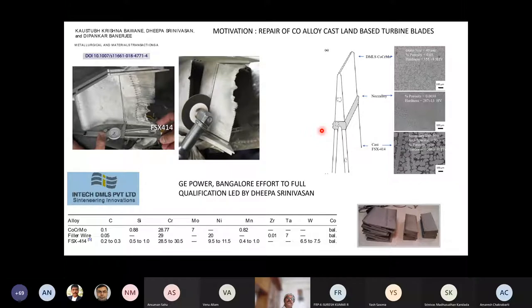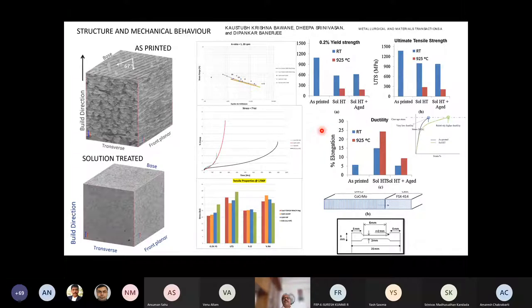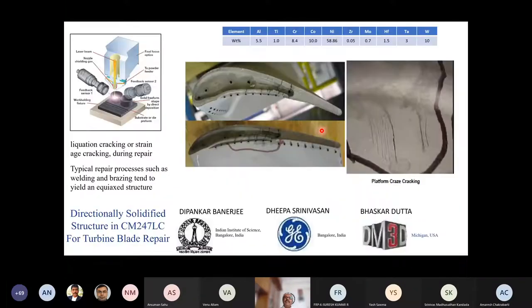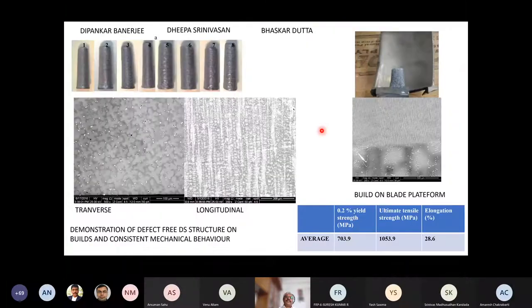So this was done for the repair of turbine blades, and this work was also done in collaboration with Intech DMLS. That's Professor Banerjee's work. I was not a part of it, but I just wanted to show it. So these people cut a damaged blade and then tried to fill it. The cracks were tried to be filled up with a new deposit, and the microstructure and properties of the deposit were analyzed, and found to be very appropriate, suitable and compatible, and therefore the blades could be repaired. This was done on CM247 blades, and this was successfully demonstrated.